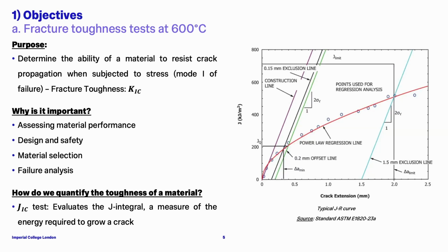And how do we quantify the toughness of a material? Well, we can do a JIC test, and this is what I've done for my research, that evaluates the energy required to propagate the growth of the crack within the material. And on the right-hand side, you can see an example of a J-R curve we might expect to obtain at the end of the test. And we'll see later on if I manage to obtain this curve.